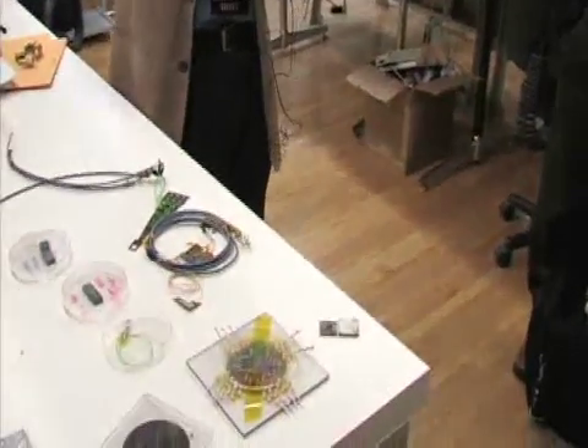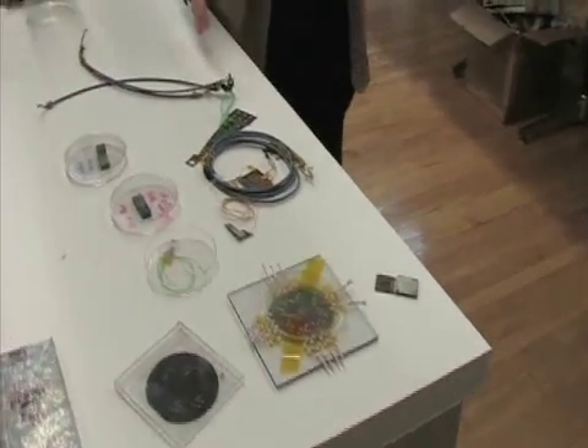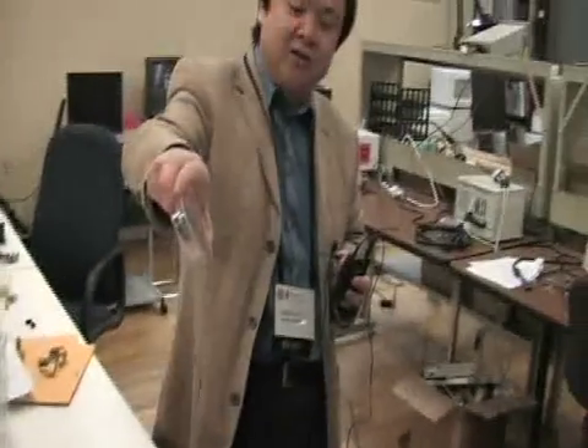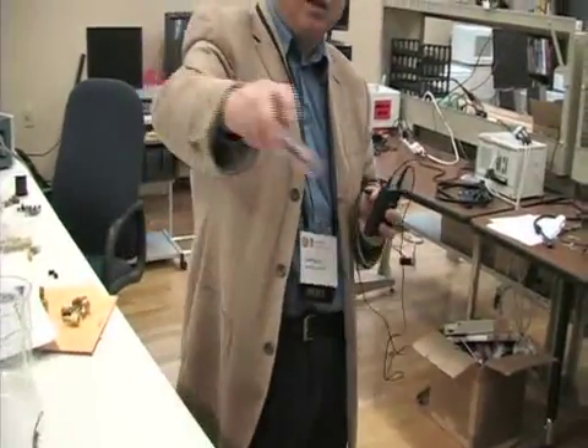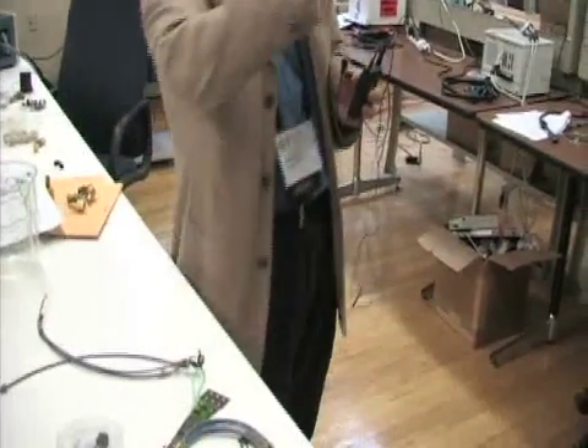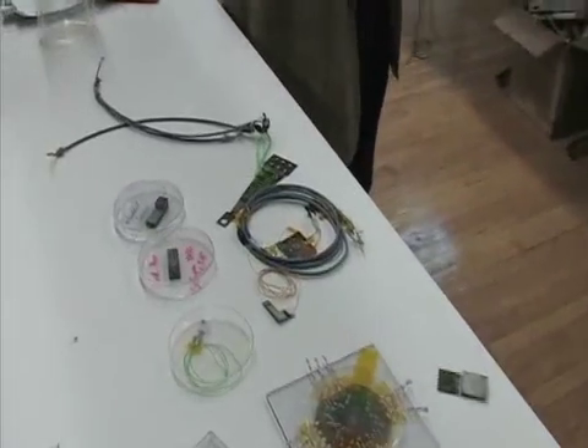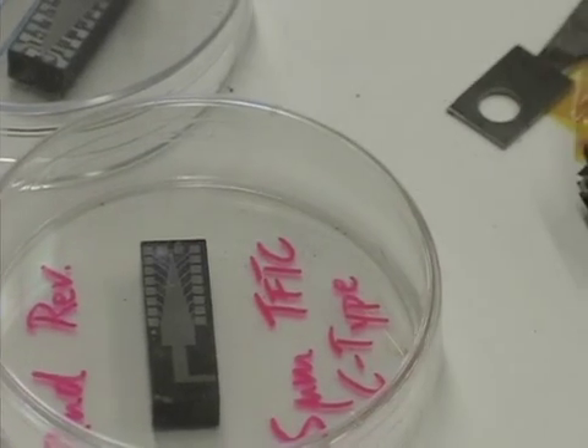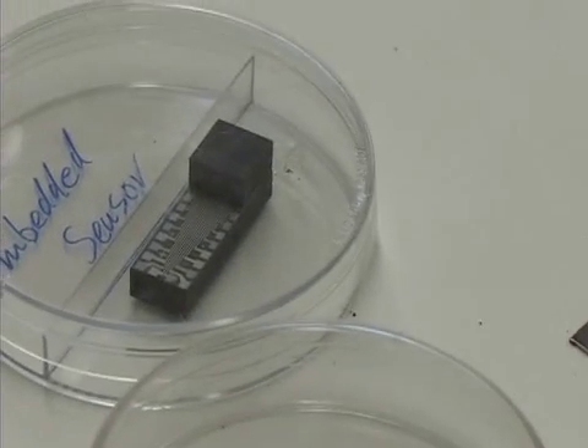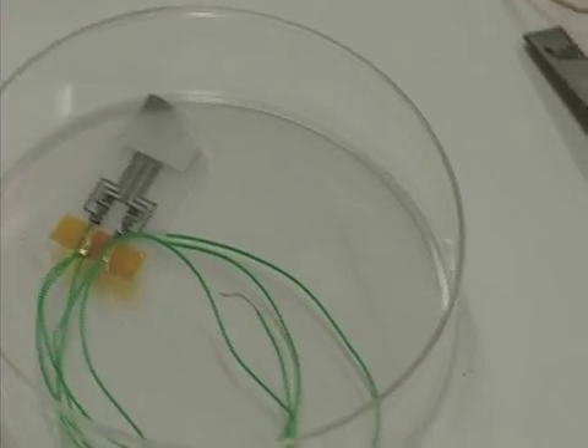And if we embed into the materials, so-called structurally integrated micro nanosensors, right, into the structure like we did, you can see later on all the sensors embedded in metal or in ceramic toolings, like we also have here, before the embedding of sensors and after embedding. So this one can be used as a cutting edge, right, with the sensor very close to the tool workpiece interface. And we really can get our sensor as close as 20 micrometers away from the cutting edge. Traditionally, the best in the world, you can get to about 500 microns. Okay, because if you get less than 500 microns, your sensor gets too noisy. It just cannot function well. And our sensor, just recently we demonstrated we can do that.